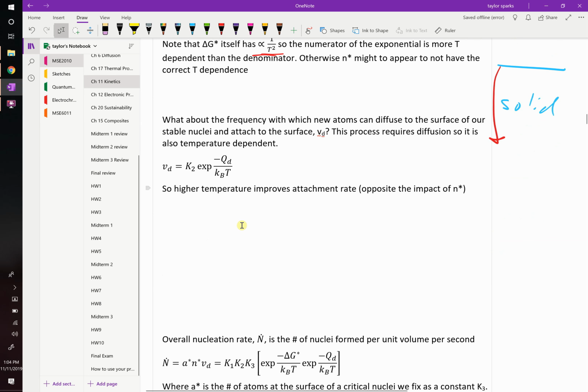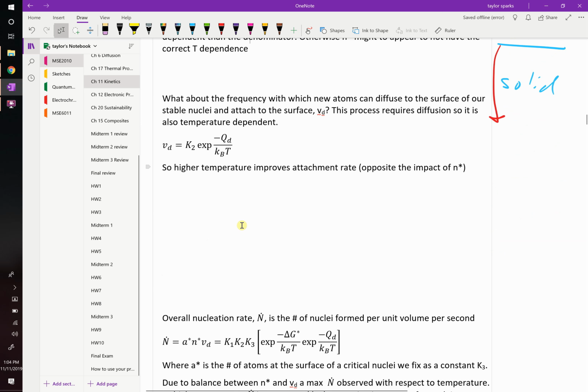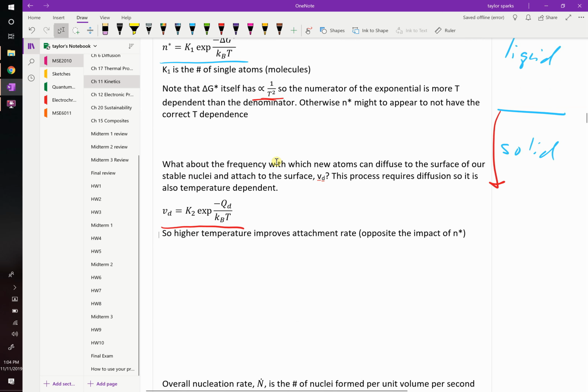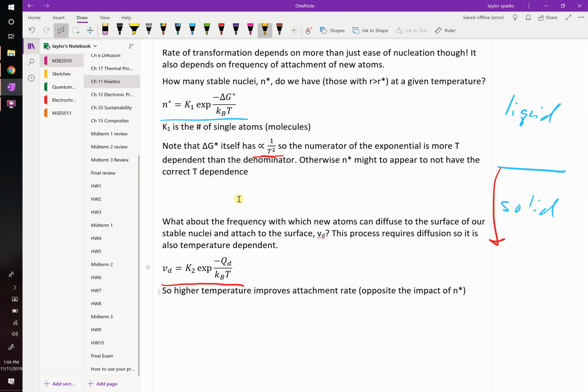Now the next thing we have to know is once you have nuclei, something has to attach to them, right? And the rate at which you get things attaching to them, we're going to call that V sub D. Sometimes you can think of that as like drift velocity. The attachment velocity, they call it, V sub D, is also equal to a constant, this time K2. It's a different constant than before. And then this one is multiplied by the exponential of negative Q_D, that's the activation energy for diffusion, divided by thermal energy. So that one has the proper temperature dependence like you'd expect. At higher temperatures, as you move up, you get faster and faster diffusion.